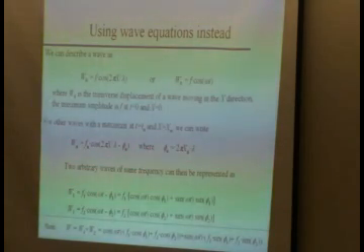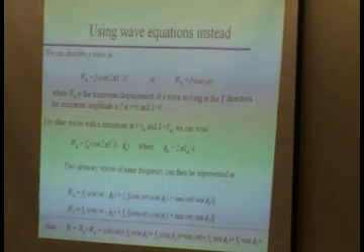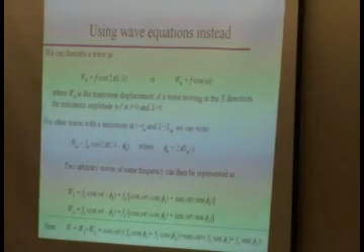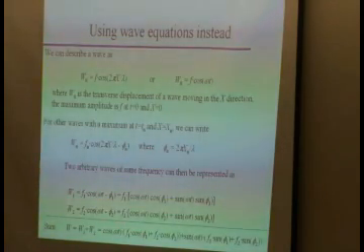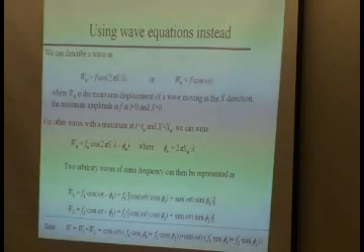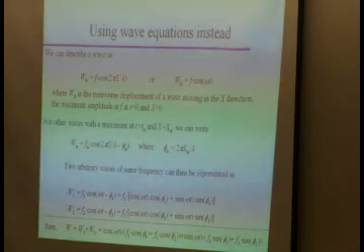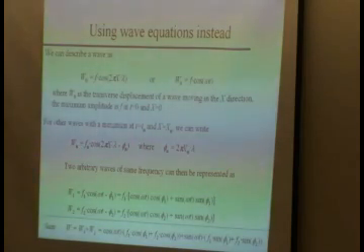Now this is really what describes the frequency of the wave, right? So as you can see, that is a term that we can draw out of that sum. It applies to all of the waves. And so if we had a whole bunch of waves, we could write this as the cosine of omega t times the sum of all f_n times cosine phi_n, plus the sine of omega t times the sum of all f_n sine phi_n. Okay?